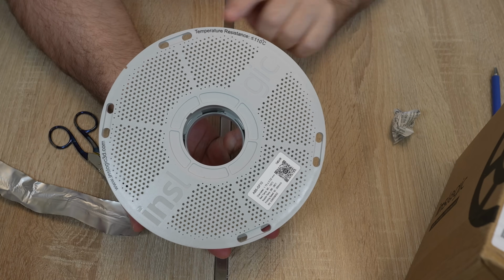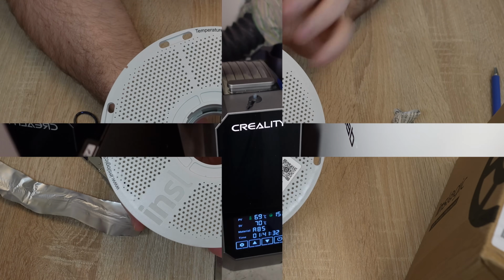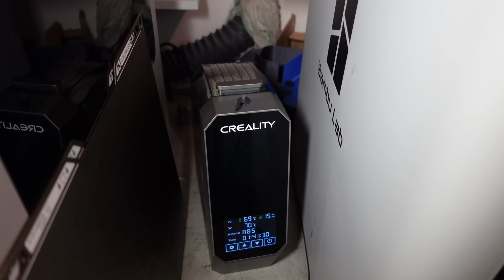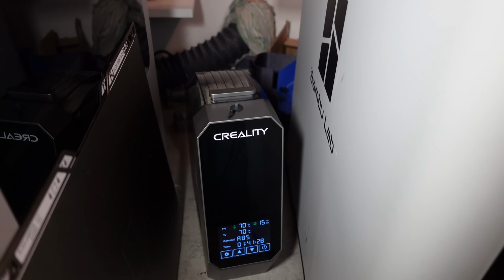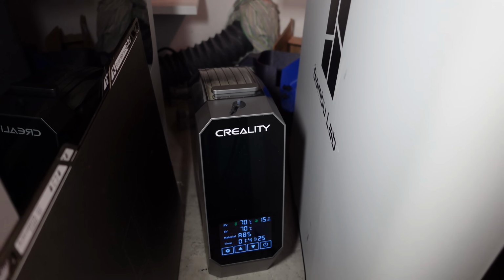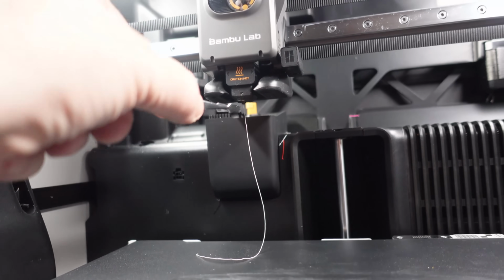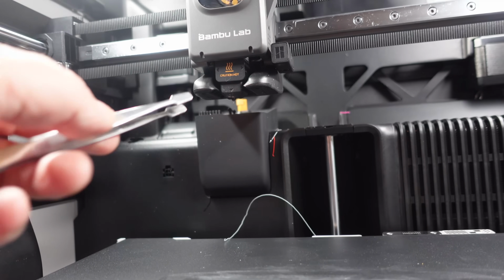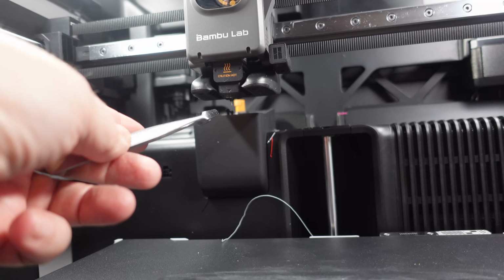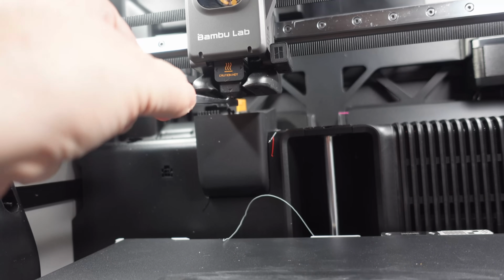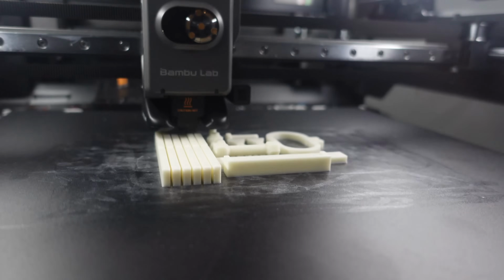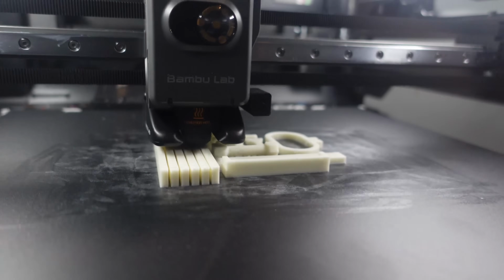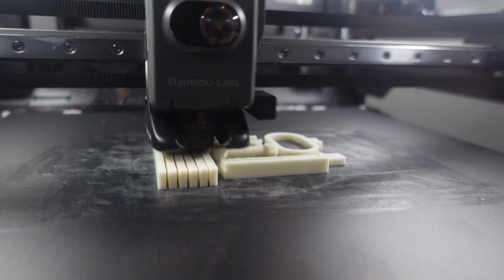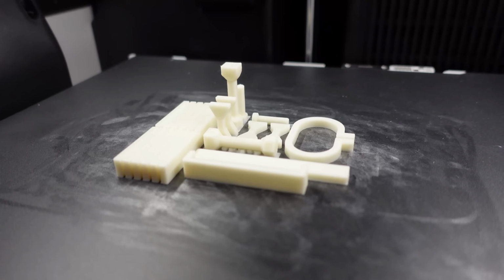Yes, the spool is designed for this, but the filament not. Drying will be at 70 degrees Celsius, 6 hours. Glass fiber version, so it should be okay. Now it looks like a dry filament with very minimal oozing. Definitely looks much better now. I will show you later side by side two objects before and after drying. Finished overnight.